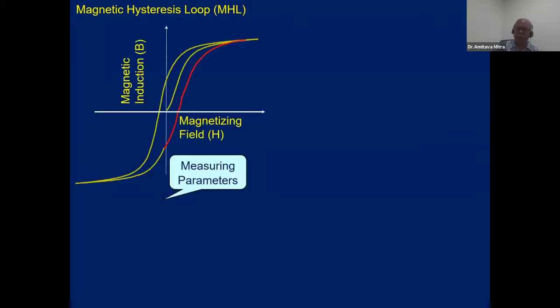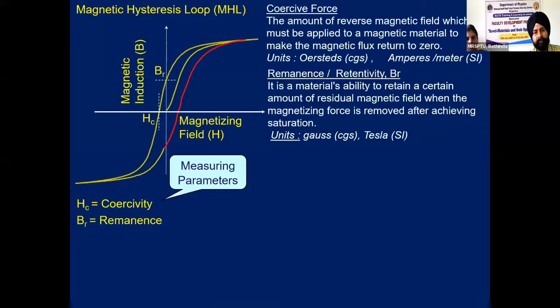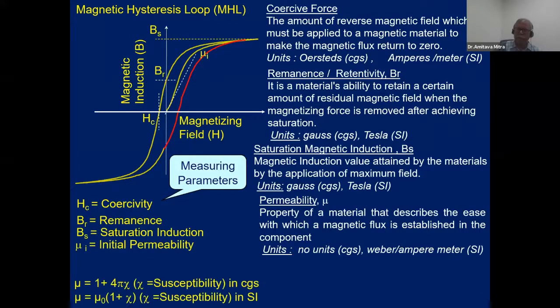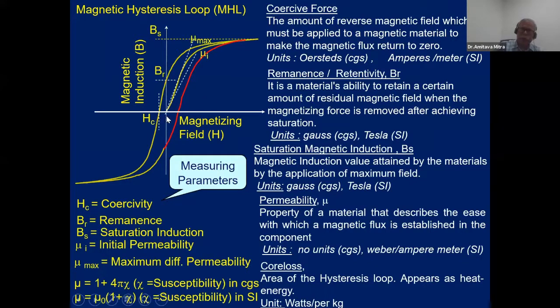After preparation of this material, we have to go for evaluation of magnetic properties, and basically we are interested in this hysteresis loop. There are a few parameters: the coercivity, which should be as low as possible for this soft magnetic material. The slope of this curve is called the permeability, which should be as high as possible, and the saturation magnetization, which should also be as high as possible for this material.